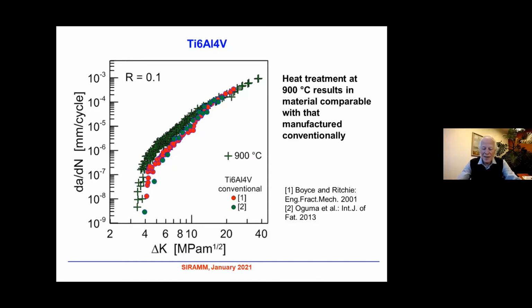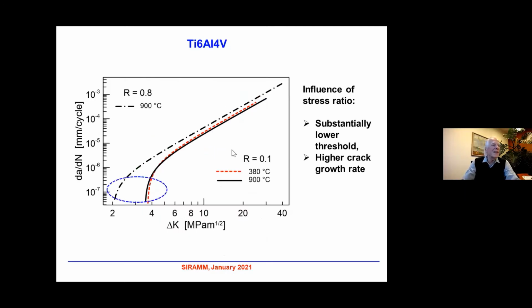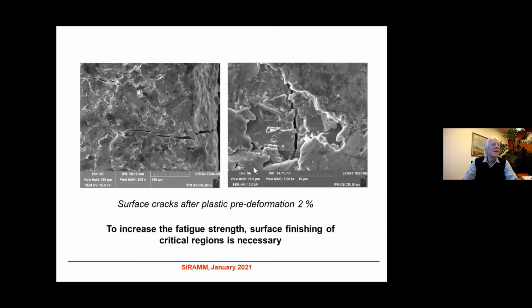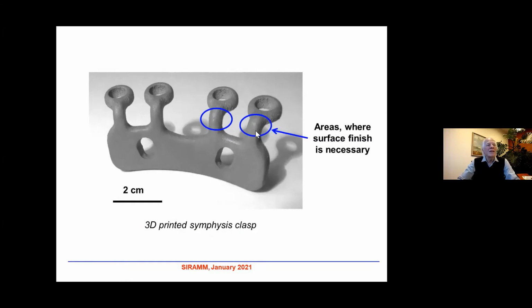As built. Now we are performing experiments where we polish our specimens. Exactly here, just a moment, if you see my presentation, we are now playing with surface finishing of these parts on these slabs. We try to have material which is as-built, material after ballotining, and material which is polished in conventional ways. And we would like to measure the fatigue behavior of the material to say whether it is possible or not to use this procedure for polishing. Naturally, if you polish the material very well, you can reach better results.